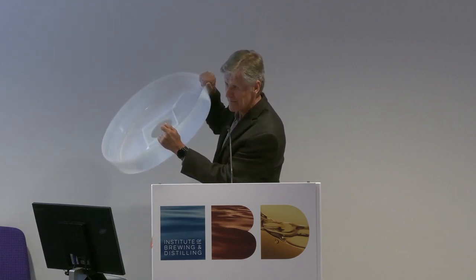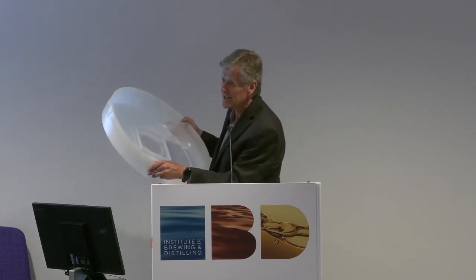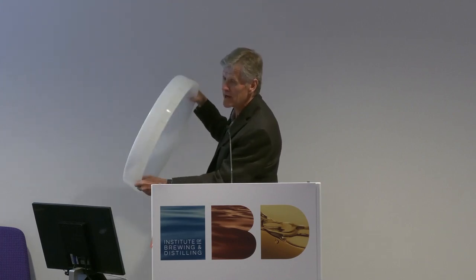How does the fit work — is it one size fits all? It comes with three different elastomer thicknesses to accommodate older traditional barrels at a slightly smaller diameter versus the standard 200-liter American bourbon barrel, and even variations within those sizes. The elastomer may go on some barrels slightly loose initially, but within days in the high ethanol environment it swells and gives a snug fit. There may be occasions where staves are slightly out of alignment with slight gaps, but for the majority those gaps are filled. And the caps are reusable.